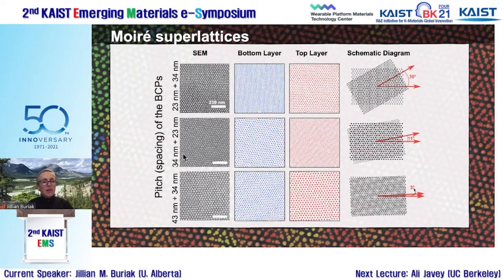He took a small plus a medium, a medium plus a small, and then a large plus a medium, and we simply put them together using Brian. And then you see these either triangles or what we call flower patterns. Brian would then use his algorithm to separate the bottom layer from the top layer, which then allows you to determine that angle of offset.